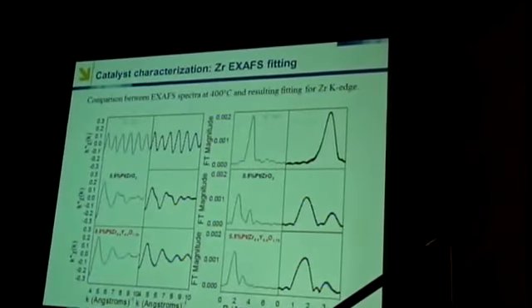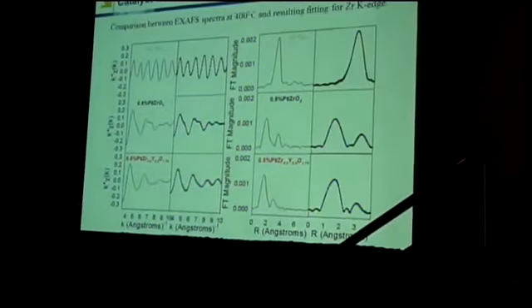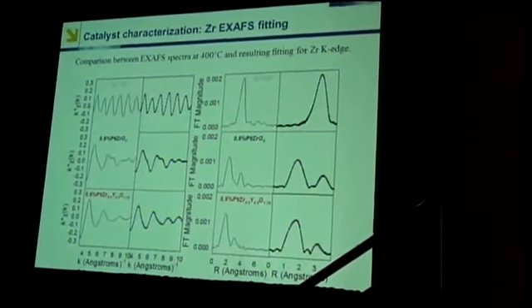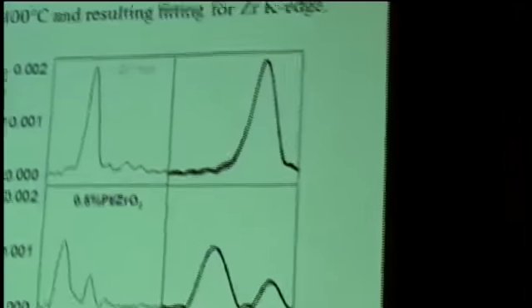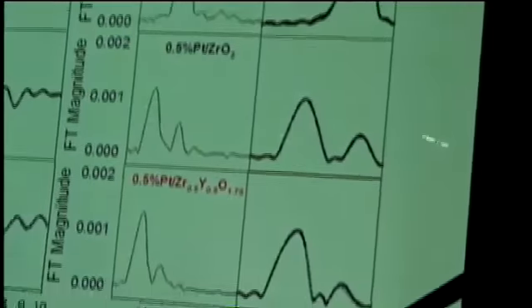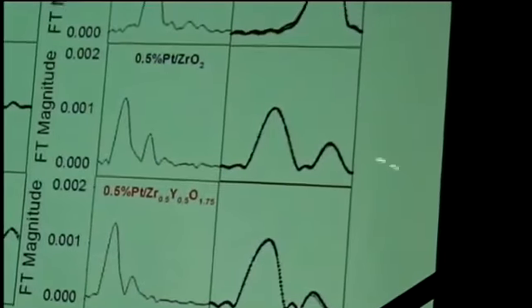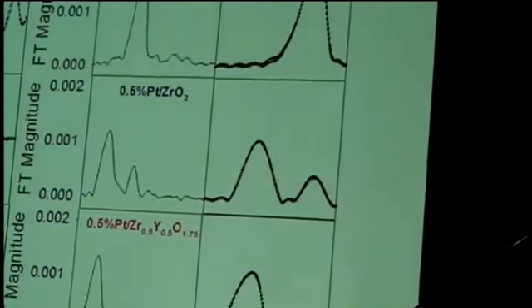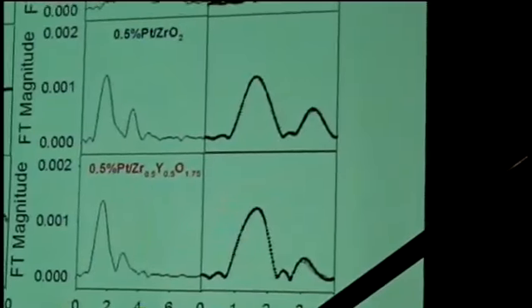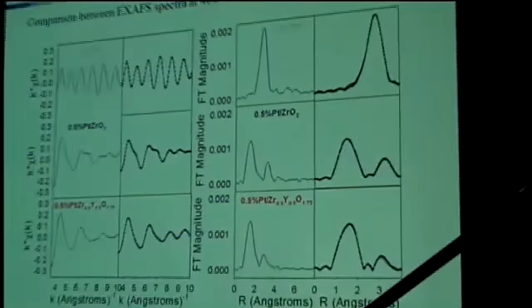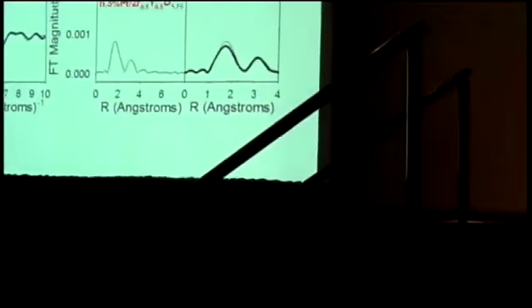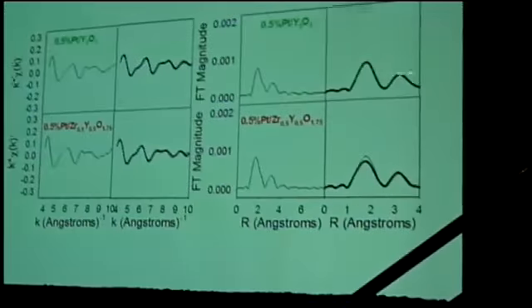We also carried out EXAFS of both the zirconium K and yttrium K edges, using the structure for tetragonal zirconia. This is the zirconia foil. Tetragonal zirconia was used to fit the undoped catalyst after activation. And we used the cubic structure, simultaneously fitting the zirconium and yttrium K edges, and we were able to obtain a reasonably good fit. And we also fit the yttria, which is also cubic, and we were able to obtain good fittings for those structures.